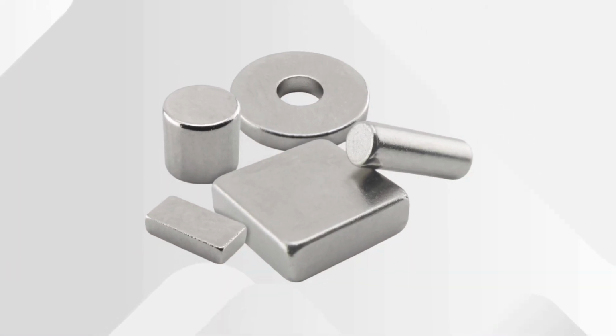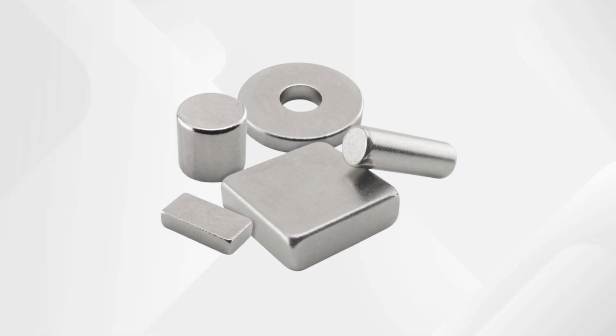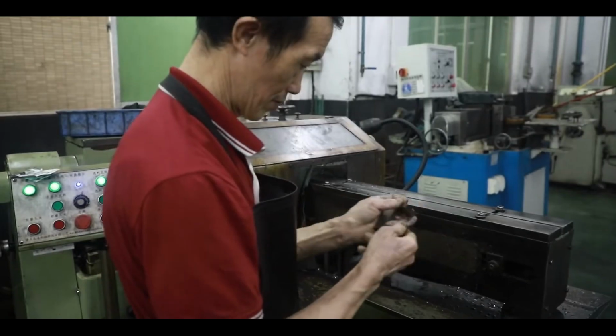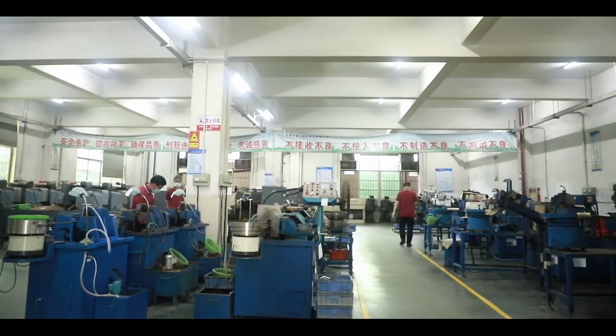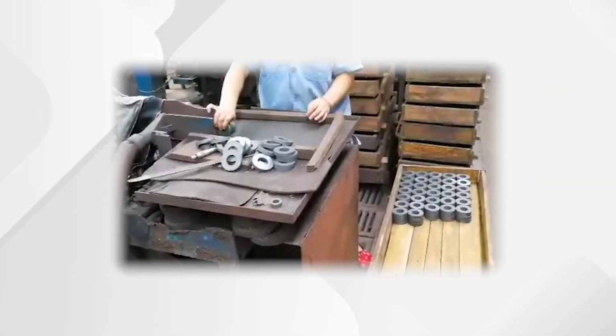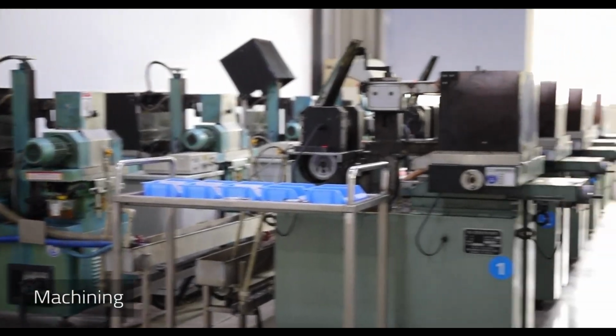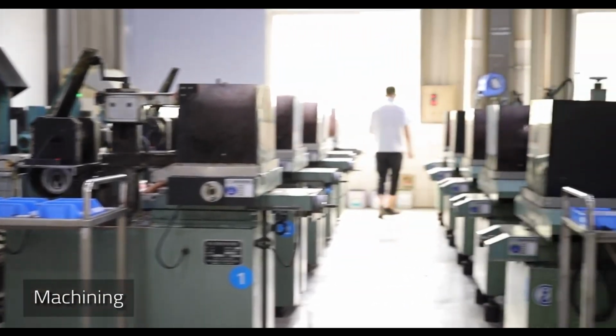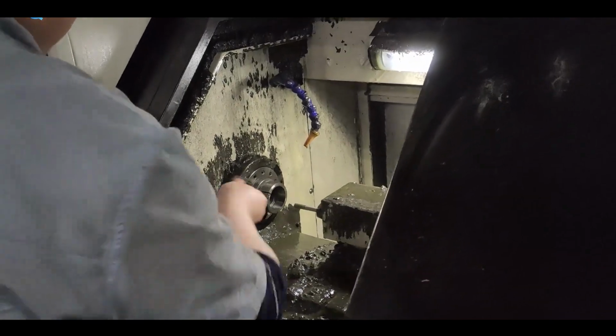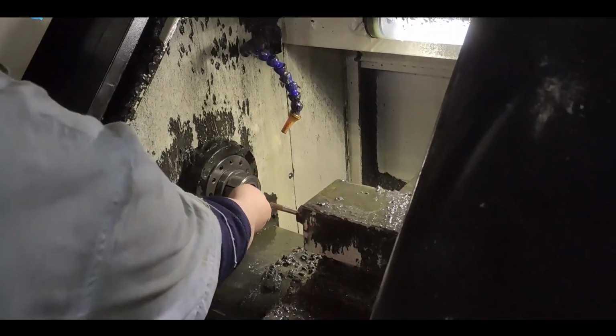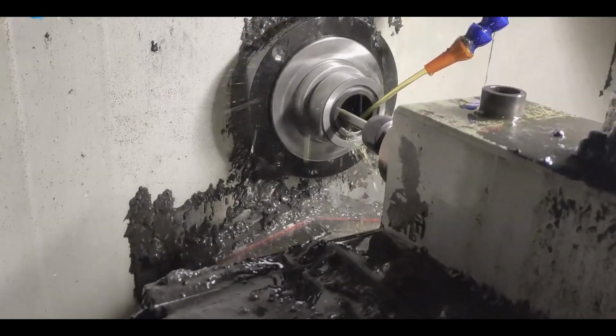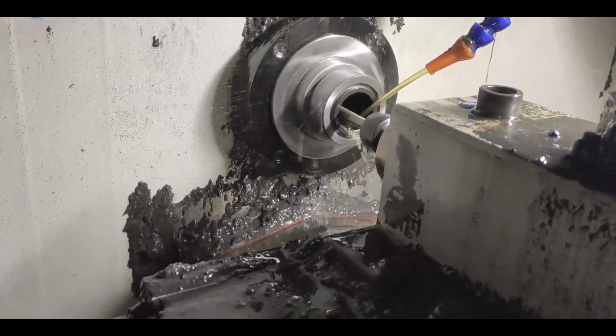During sintering, the magnets shrink about 15–20% linearly. Completed magnets have a rough surface and only approximate dimensions. They also exhibit no external magnetic field. Finishing: sintered magnets receive some degree of machining, which can range from grinding them smooth and parallel, OD or ID grinding, or slicing block magnets into smaller parts.